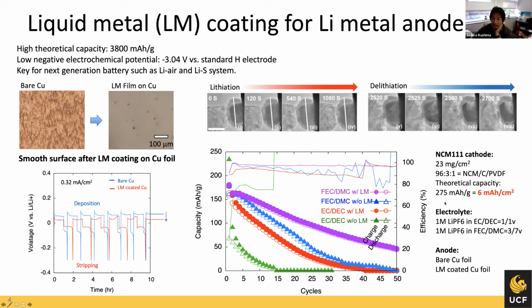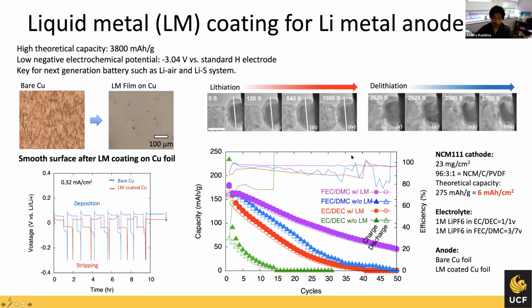So this is the combined full cell with significantly large capacity. You can see from non-coated copper to the liquid metal coated copper with a different electrolyte, you can significantly enhance the cycle lifetime. Okay, so that's for the materials development side.